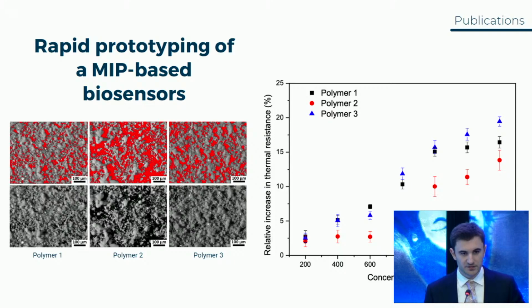And in particular, we show that polymer 3 has an increase in the response, especially at higher concentrations. So we can say that this study can open up the possibilities of more in-depth future studies when the heat transfer method and molecularly imprinted polymers are used together.